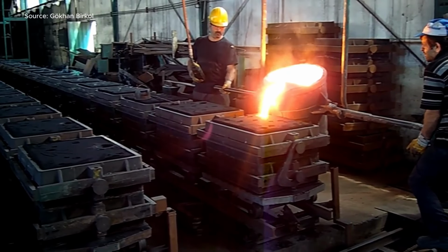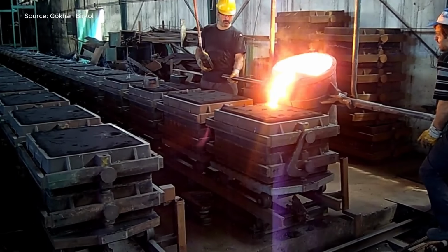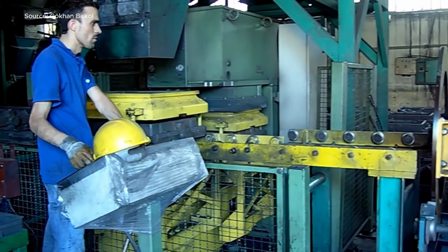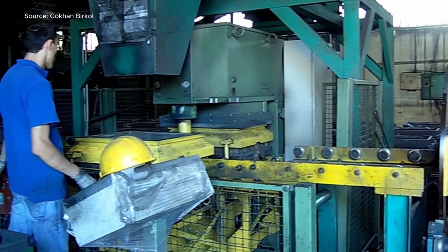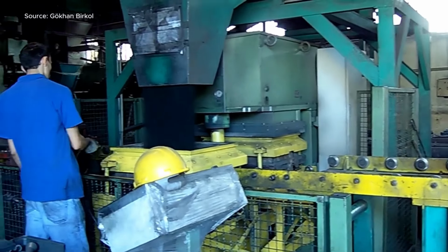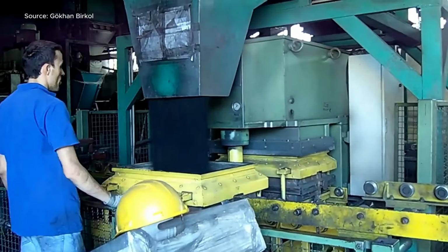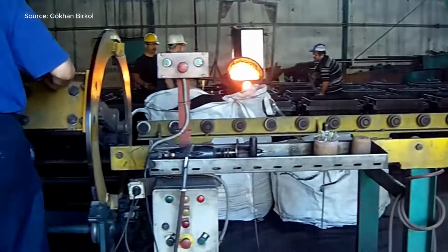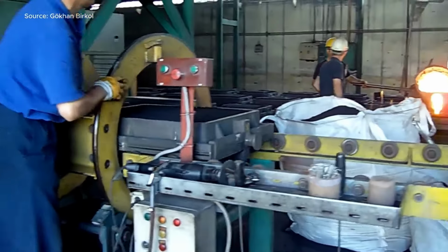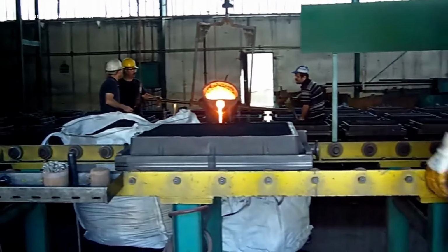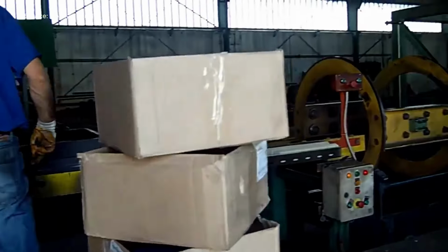The process starts with melting pig iron and scrap metal in an 8-ton induction furnace at 1,300 degrees Celsius to 1,500 degrees Celsius, taking about 1.5 to 2 hours. The molten metal is alloyed with 2% silicon, 1% manganese, and 0.5% carbon.